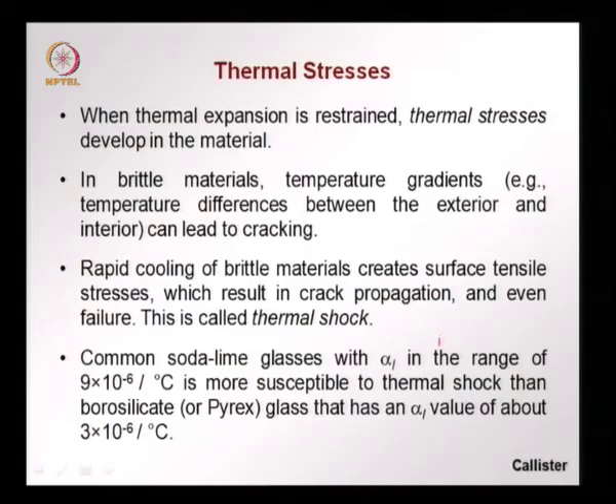On the other hand, we can have glass with lower alpha L values, coefficient of thermal expansion could be lower, like in the case of borosilicate or pyrex glass that is used for heating materials, even for cooking, in the stoves and so on, we use borosilicate or pyrex glass. This has a coefficient of thermal expansion that is about 1/3 that we see in common glasses. So, this is less susceptible to rapid changes in temperature and less susceptible therefore to thermal shock.